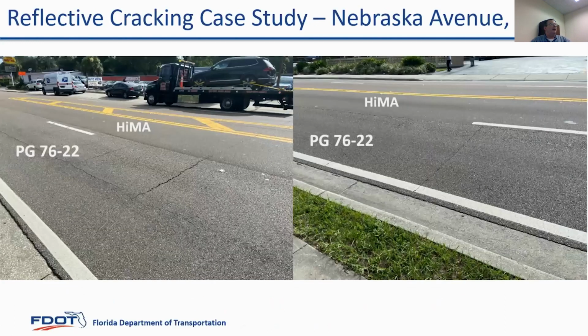And then I want to thank Gary Fitz. He gave me these pictures yesterday for the webinar. And you can see the difference. In this picture, you're getting some transverse cracking across both lanes. There's the 76, there's the HiMA, but you can see there's a significant difference in the width of the crack. It's a lot less in the HiMA lane. And in this picture on the right, you can see the crack basically goes away in the HiMA lane. So again, a big difference in performance between the 2 mixes.